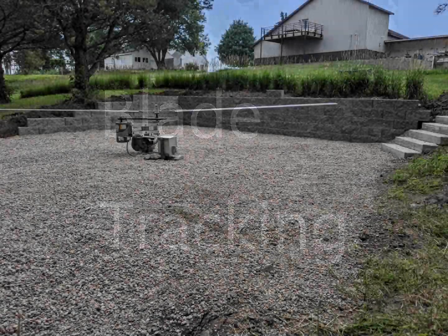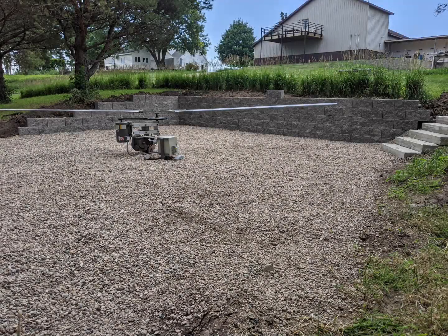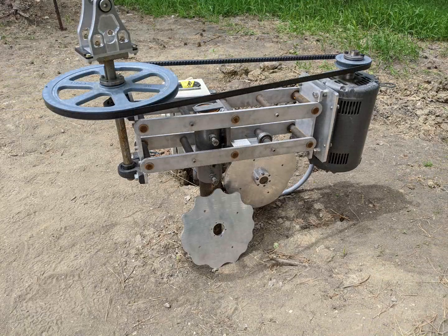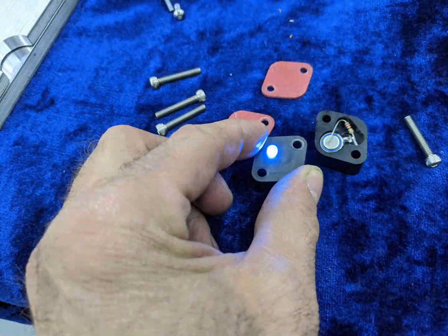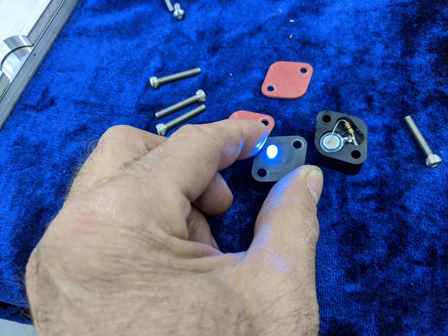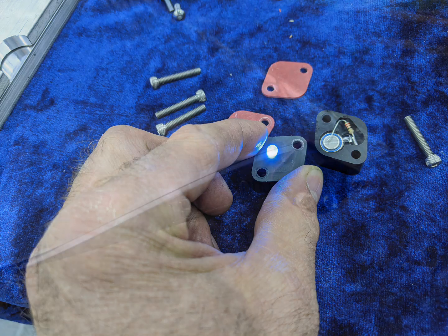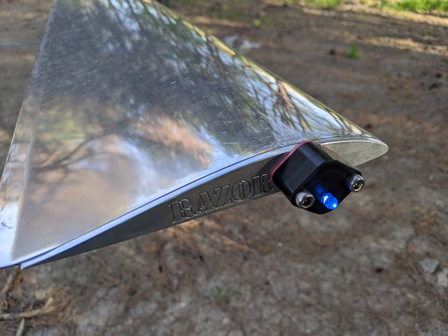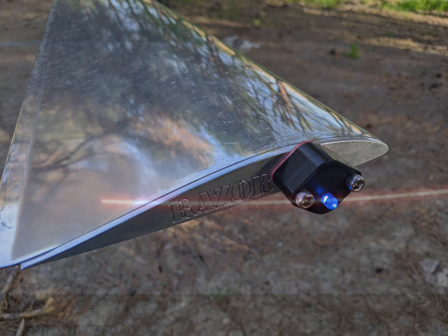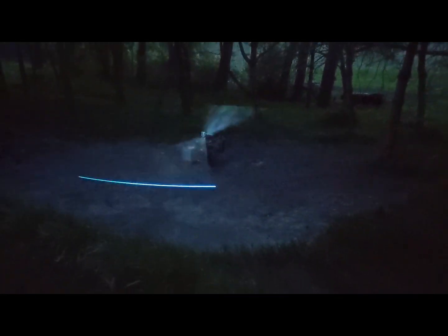The next step to calibration is to ensure that both blades are running in the same plane. We do this with blade tracking. This is performed on our test stand. To view the blade position, we use LED lights on the blade tips, which are much more visible and accurate than a reflector system. These are bolted to the tips of the blades, and they're brought up to a test speed and monitored. Now please note this is not in any way a true representation of the forces that the blades will see in flight, but it is a very good starting point to build upon to assure the smoothest performance available.